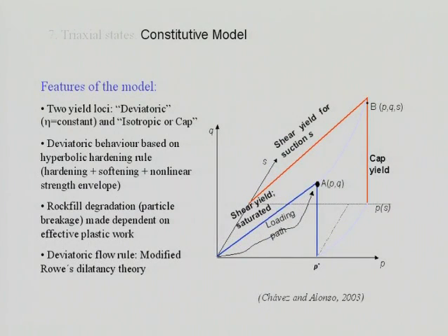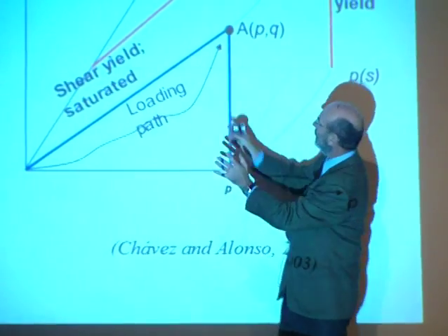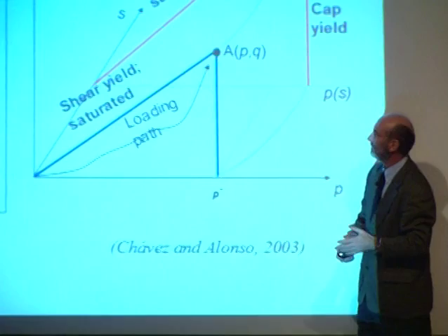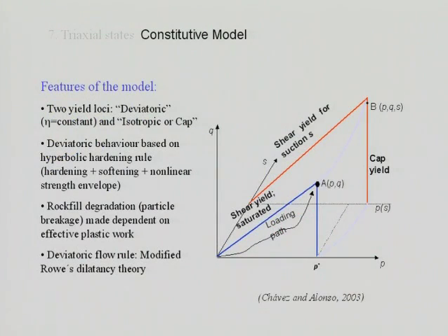And in a p-q-s plane, perhaps one of the simplest ways to formulate a model is to select a cap, which is simply this line here, and then the effect of shearing is taken into account by this eta equals q over p constant line, and then this is extended into the suction regime. But this is not that far from this yield curve that we have seen before, coming directly from the experiments. There is a paper published recently in Soils and Foundations. You may have more details.